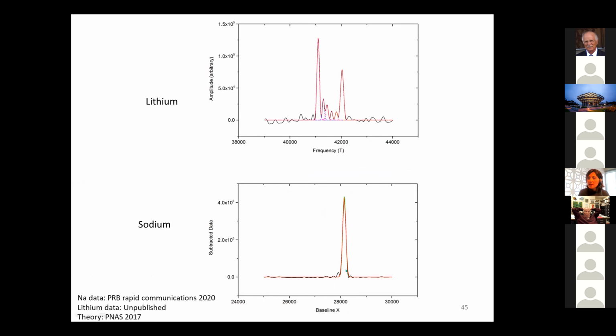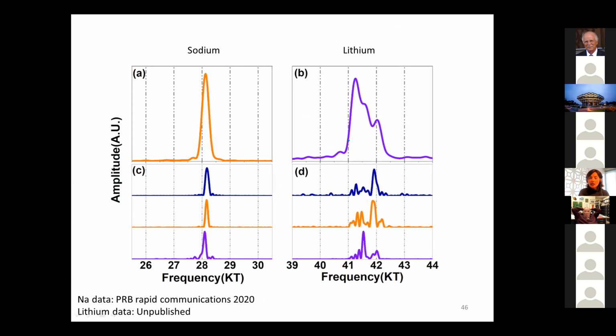So the next thing that we did is that we moved this experiment. We were confident that we are seeing this splitting, and we have done lithium and sodium side by side. We did lots of measurements, and these two, A and B, show that as we change the orientation of the sample, we are adding up all these peaks, and this is what we get. Lithium has this broad peak. This is the same frequency interval, and the range is the same. Values are different, but the range is the same. Sodium is a sharp peak, whereas lithium is very broad and distorted.